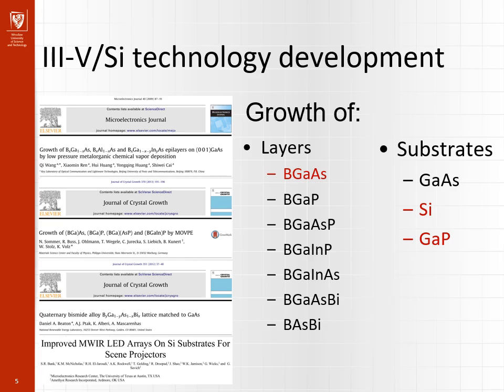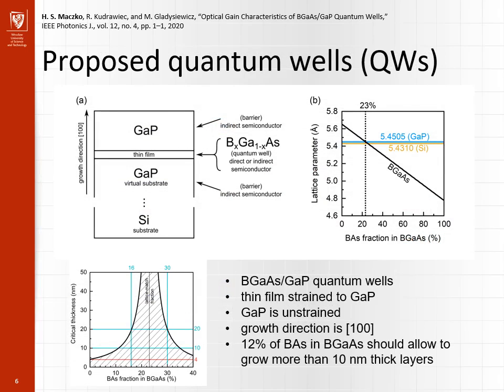This allows to create gallium phosphide virtual substrates through heteroepitaxy on silicon. Those are the reasons why boron gallium arsenide and gallium phosphide were chosen by our group to analyze them theoretically as the materials of novel quantum wells. The proposed structure is made of a boron-gallium arsenide thin film covered with a gallium phosphide crystal on both sides, all such that can be grown on silicon wafers.